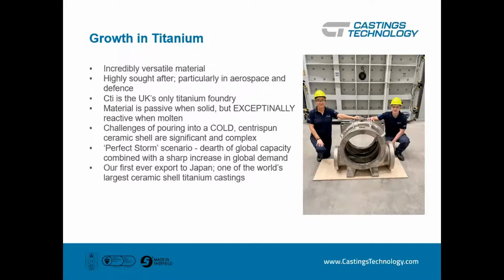And the thing about titanium is it's very inert, very strong, very light when it's solid. Like most materials, it doesn't like to be molten and wants to get back to its solid state as quickly as possible. The difference between titanium and other metals is, whilst it's in that state, it's highly, highly reactive. And that means we have to work very hard on the chemistry of our prime coat, the first coat that sees the metal as it comes in. But also we have to avoid oxygen getting anywhere near it at all costs, and particularly water, which we'll come to in a second. And bearing in mind, we're still using cold shell technology, and there's only one other foundry in the world that we're aware of that's cast titanium into a cold shell.